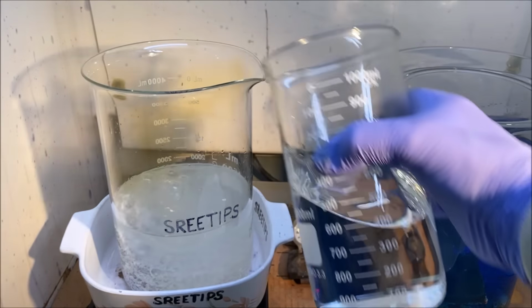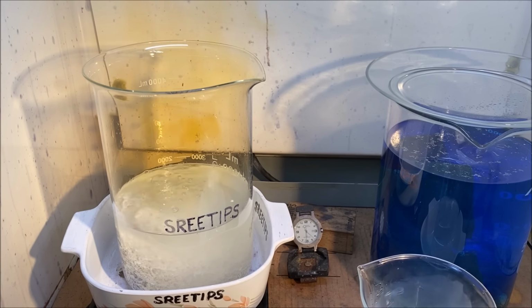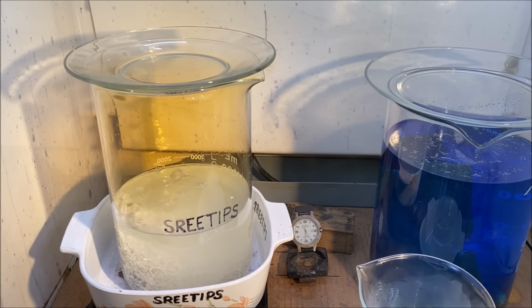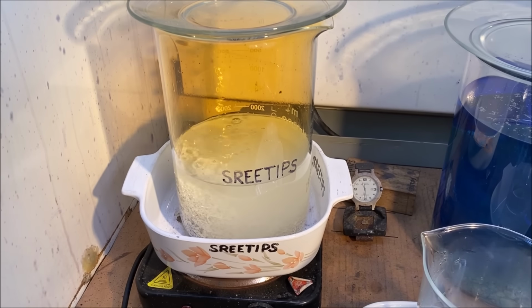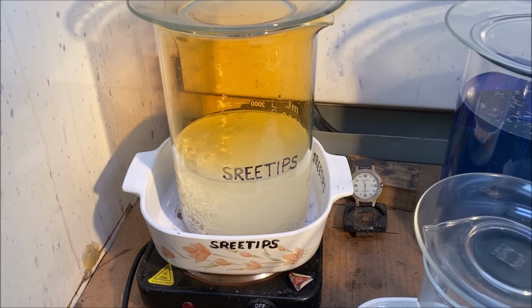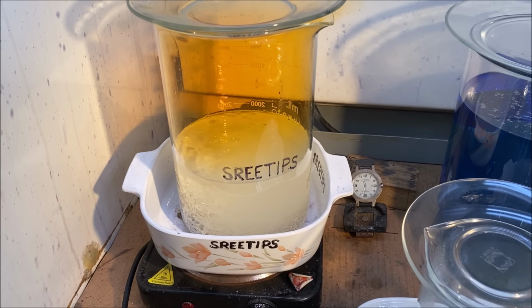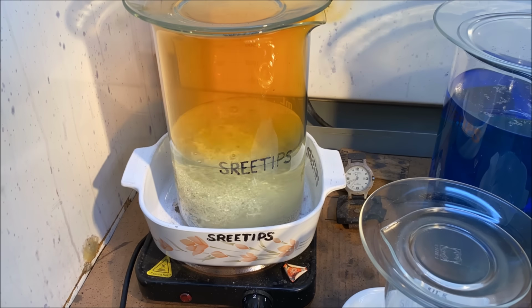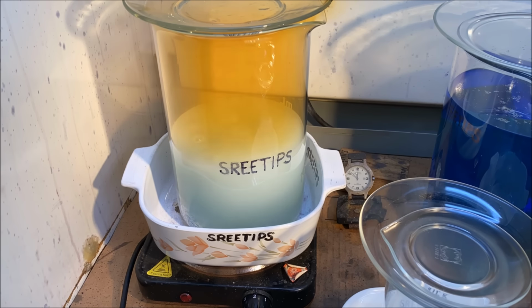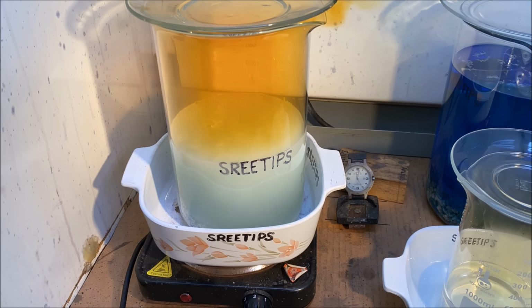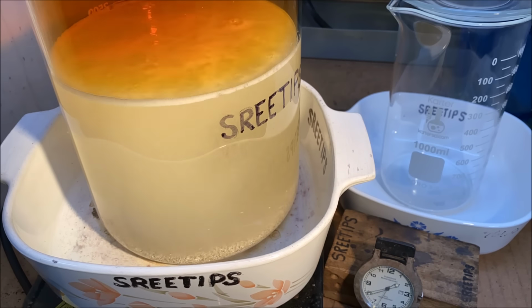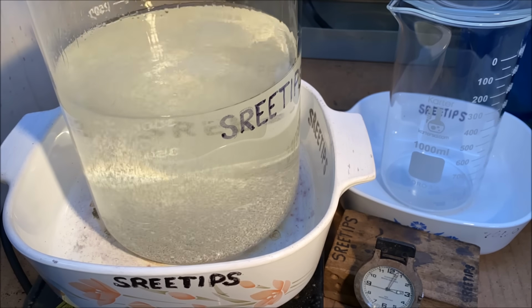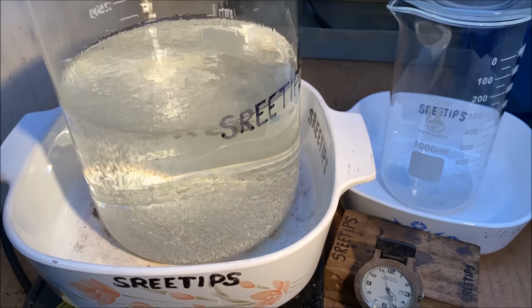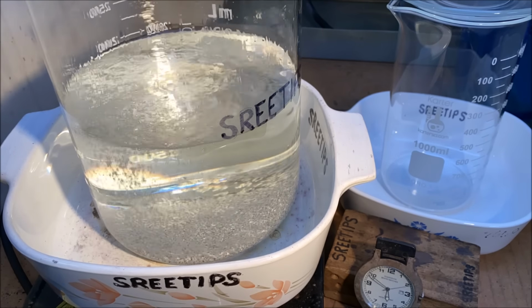I've added about half of that nitric acid. We'll just put the cover on, let this react for a little bit until it calms down, and then I'll add some heat. What I'm doing here is using hot dilute nitric acid to dissolve that 1 kilo of silver in the bottom of the beaker. When I get done with the reaction, I'll have about 1 kilo of pure silver dissolved in 2 liters of liquid. I let this cook until all the fumes clear up, and I've got just a little bit of silver left down in the bottom of the beaker.